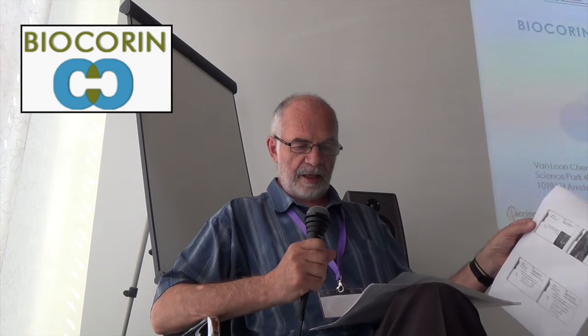Now, in that anaerobic environment of lithotrophic corrosive bacteria, sulfate-reducing bacteria produce iron sulfide, and that black crust is a layer that has electrically conductive properties. When growing, iron sulfide thickens, and underneath you can have a growth in layers, and we see by transect analysis that in a period of 2 years, up to 2 centimeters of iron of a sheet pile can be consumed.